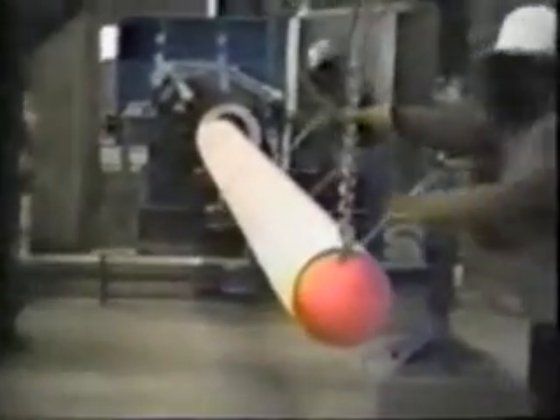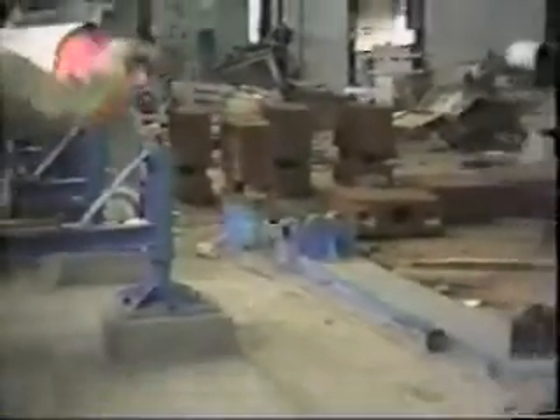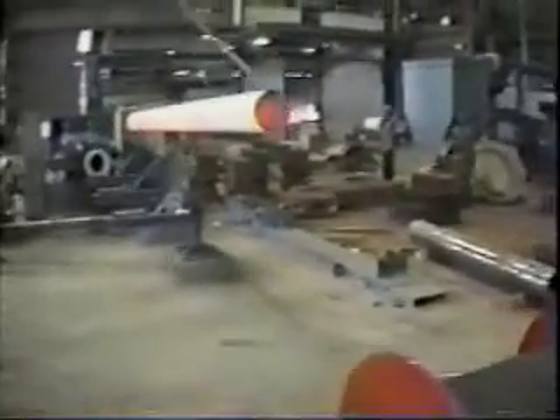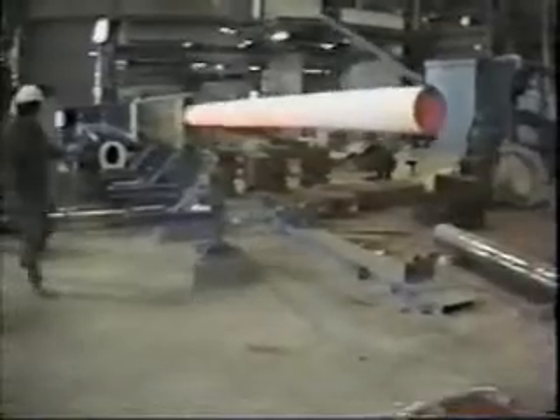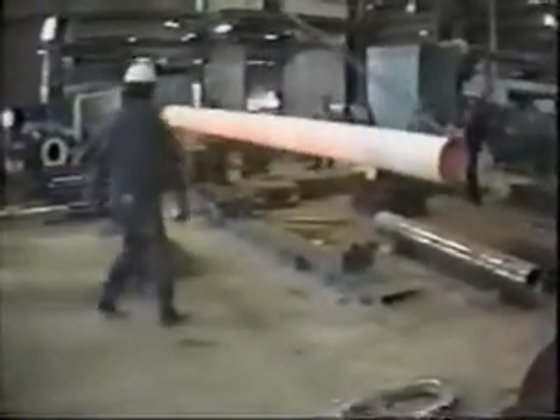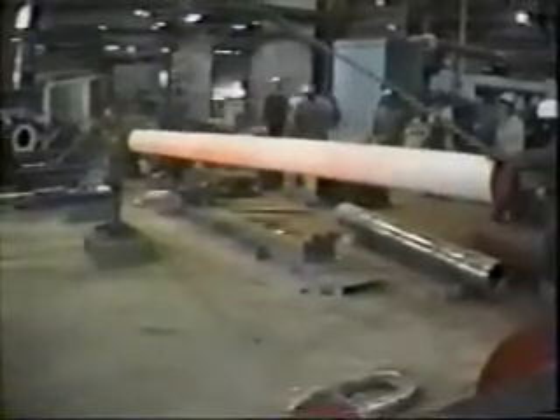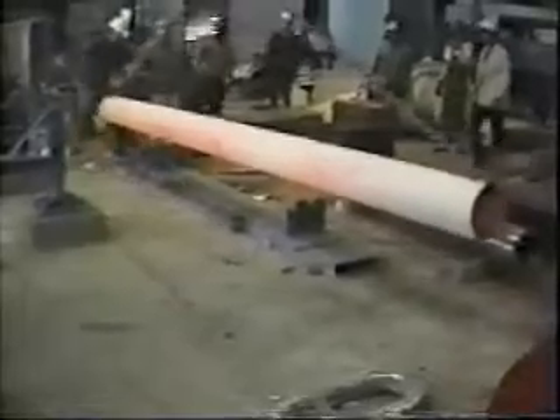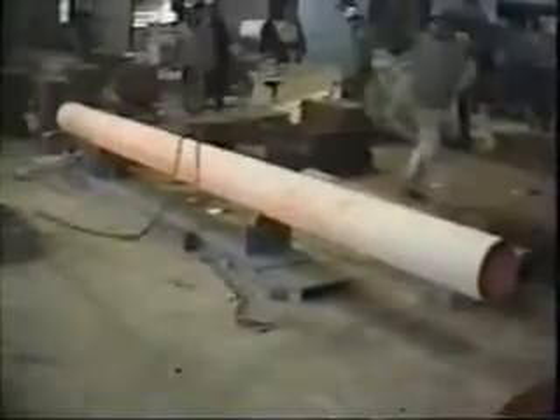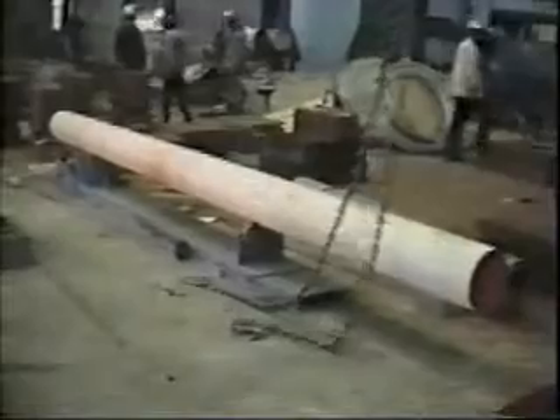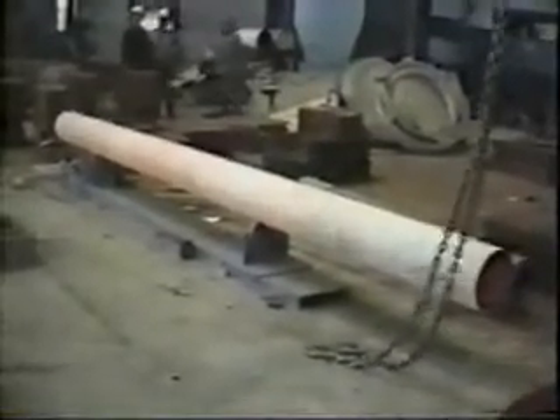The casting is then extracted to the casting supports and then lifted by an overhead crane and taken to the specially designed casting rotating assembly provided by Centrifugal Casting Machine Company. This casting rotating unit is provided to rotate tubes during their initial period after extraction to avoid warping of the casting and avoid ovality or squatting of the casting while it is still at a critical temperature. This assures a uniform, smooth, shaped casting.